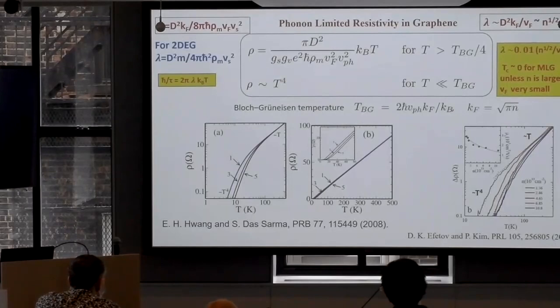And then Philip saw our paper and called me, and I said, we cannot go all the way there, but maybe we can see this T to the fourth behavior, which nobody has ever seen clearly. You know, the Bloch-Grüneisen behavior T to the fourth, you cannot really see in regular metals. It's very difficult to see. Since our density is very high, this temperature is pretty high. It's of the order of 50 Kelvin, 100 Kelvin. So you can clearly see it going from linear into T to the fourth.